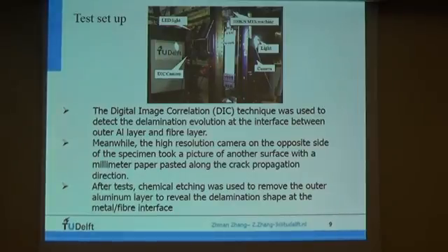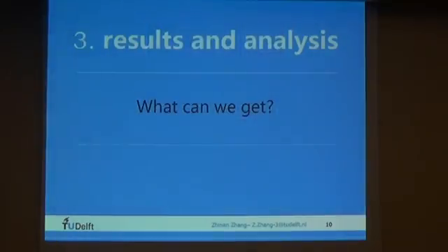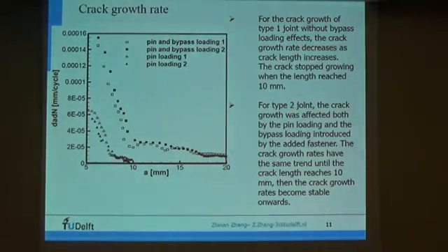After the test, a chemical agent was used to remove the outer aluminum layer to reveal the delamination shape at the metal and fiber interface. That's the procedure of the test. So what can we get from this test?